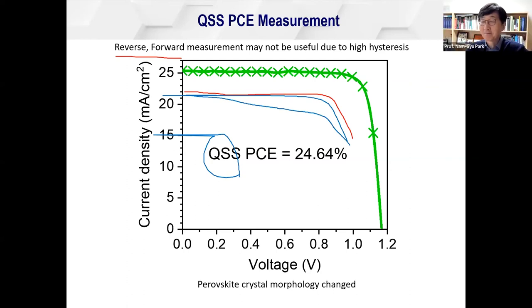Bye. Thank you, Pedro. So I'm going to ask some questions. It's related to what Pedro said about toxicity, but in fact it's about your response, because you talked about phosphates and how they can interact strongly to avoid lead elimination. We have recently reported the use of additives with phosphate and carboxylate groups. What we found is that we were unable to improve the voltage of the solar cell, which means we were not passivating deep defects, but the stability was very good.